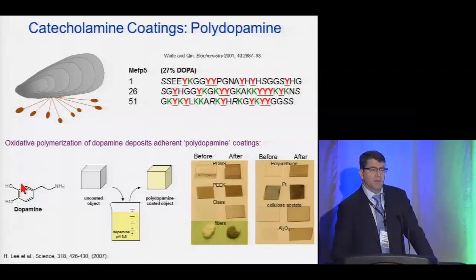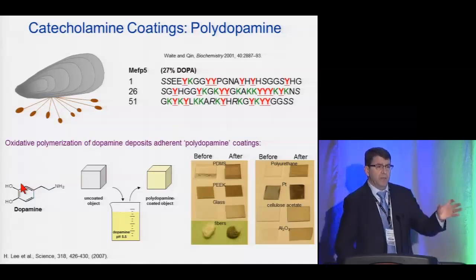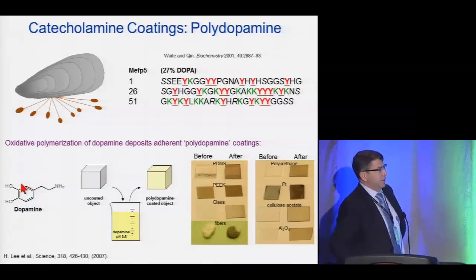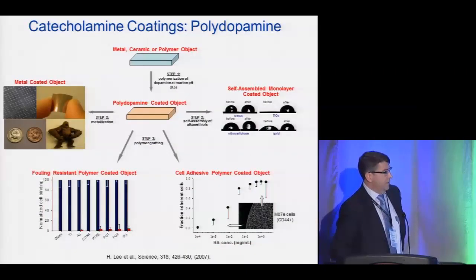You take a solid, it might be solid bulk material, it might be fibrous, might be nanoparticles, microparticles, immerse them in a solution of dopamine at pH 8.5, and out comes after a few hours a conformally coated solid. And you can see some of the pictures here that indicate this. And this works on pretty much any type of material using the same basic chemistry.